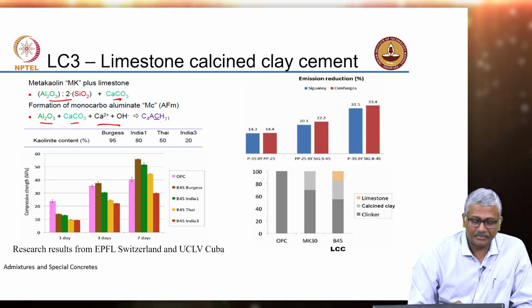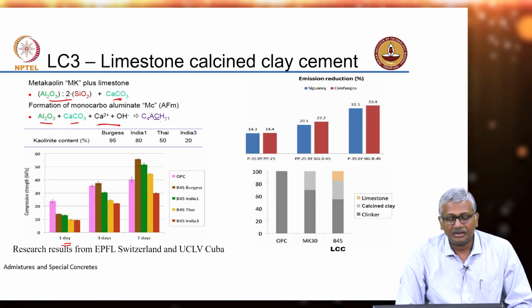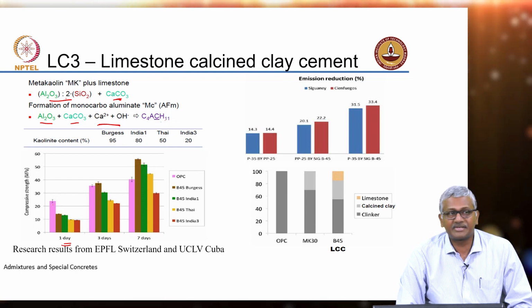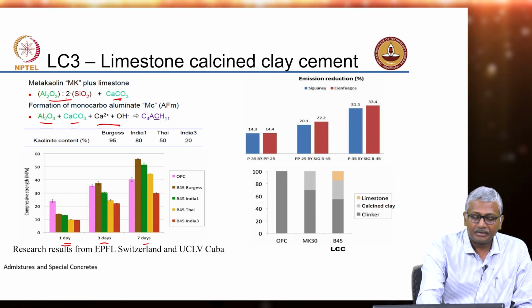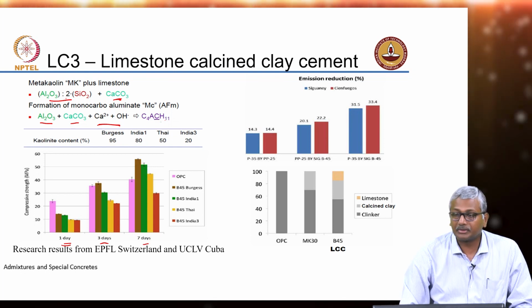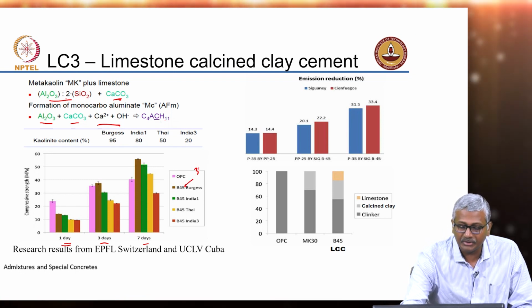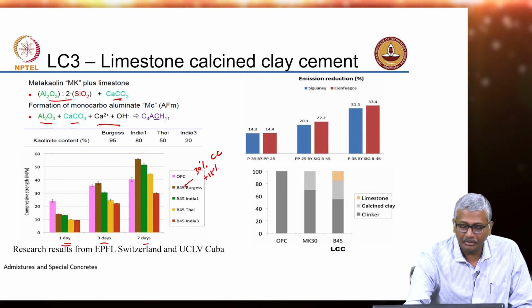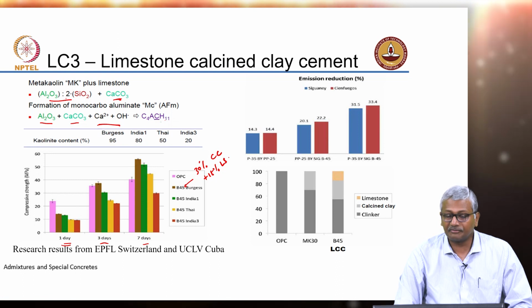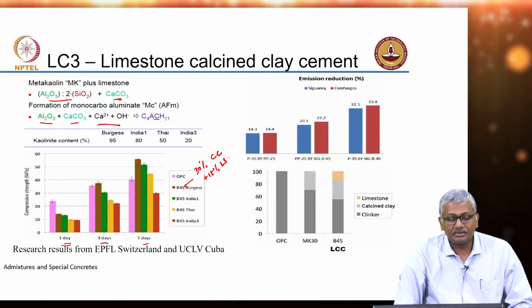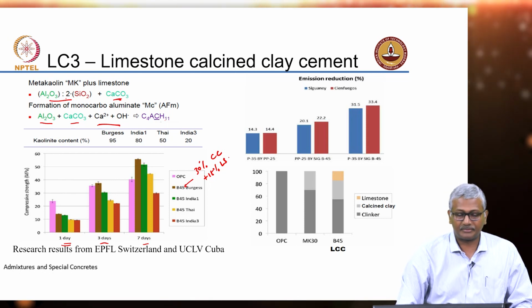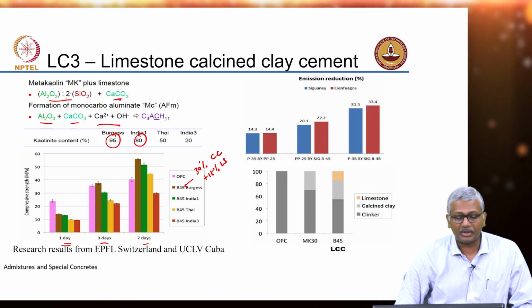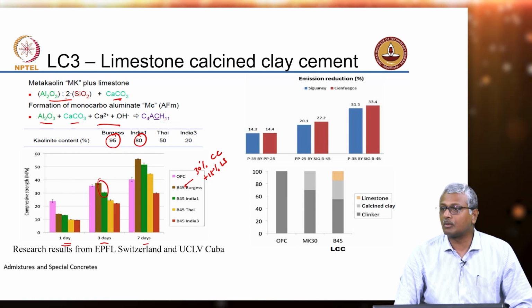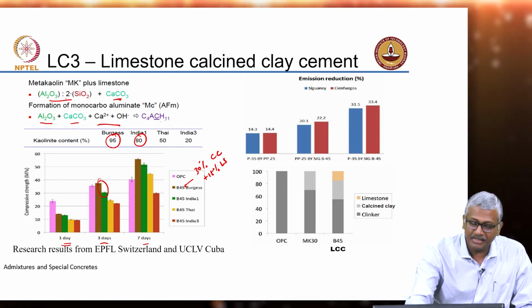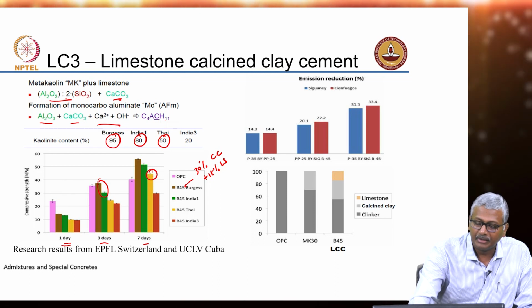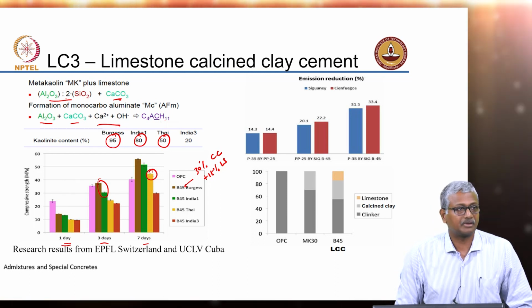Anyway, so these were some early works done by researchers on limestone calcined clay cement, where they clearly showed that the one day strengths as compared to plain Portland cement probably were not the same, but when you do 3 or 7 day strengths, the calcined clay usage along with limestone, even at a 45% replacement level, so here it was 30% calcined clay and 15% limestone. So by 3 days, the clays that were rich in kaolinite, for instance, the Burgess clay and the India 1 clay, you can clearly see by 3 days, they have a strength that is almost equal to that of Portland cement mortar. By 7 days, even the cement with 50% kaolinite has overtaken the plain OPC in terms of strength.